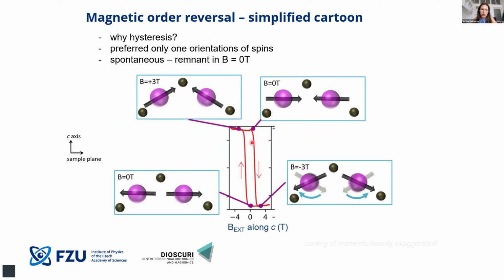However, then ramping the magnetic field down, one again has the spins aligned parallel or anti-parallel to each other, and applying a higher magnetic field further, the spins are canting, but in the now unfavorable direction. Then by increasing the field even further, the unfavorability is already so high that the spin structure decides to reorient to the energetically more advantageous configuration, which in our schematic case points towards the non-magnetic position. Therefore, by ramping the magnetic field down again to zero, the spins have no reason to come back to a different state. So then we achieve these two different pictures.